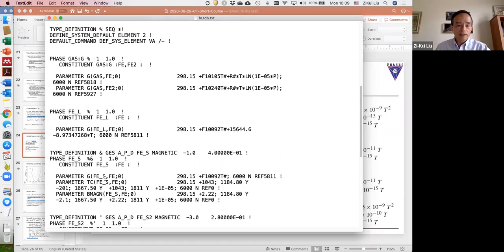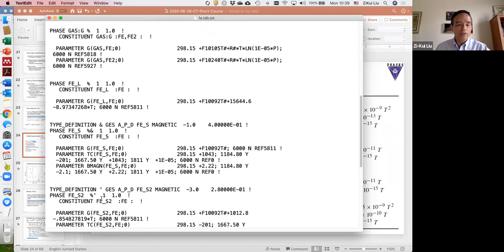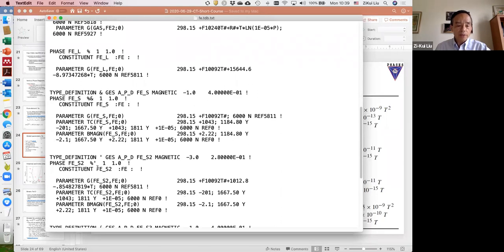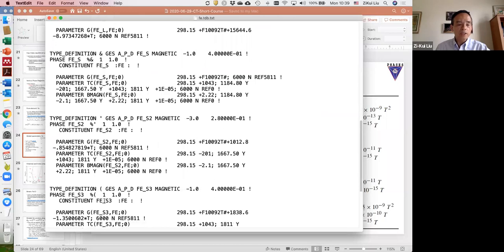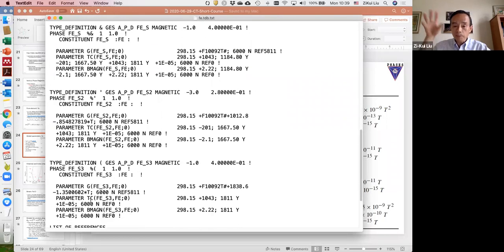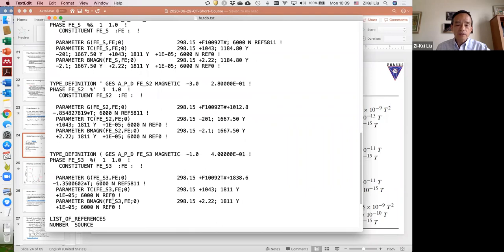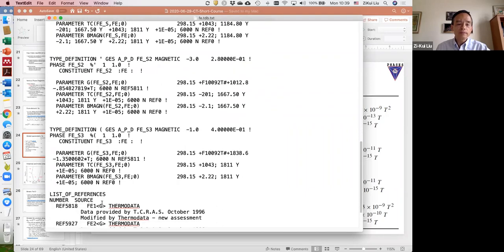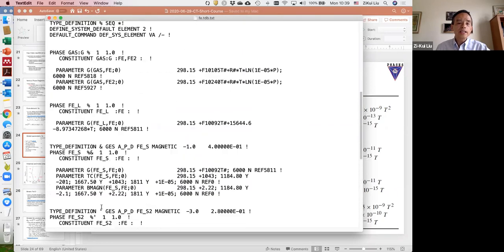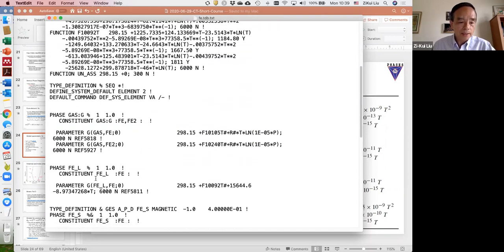You have the BCC energy, you have the magnetic contribution. The FCC phase has a magnetic contribution. You have the HCP phase, high temperature BCC also has a magnetic contribution. Then the reference here. So you see, for example, let's look at the function, the BCC phase.